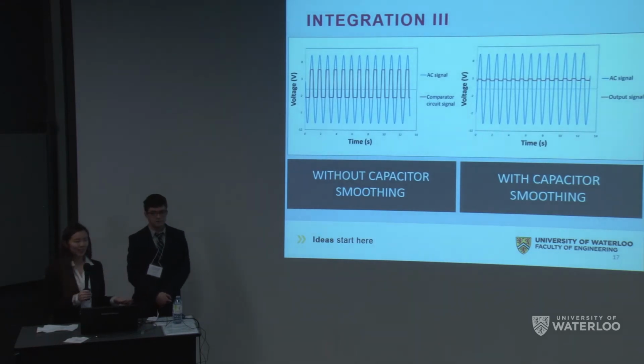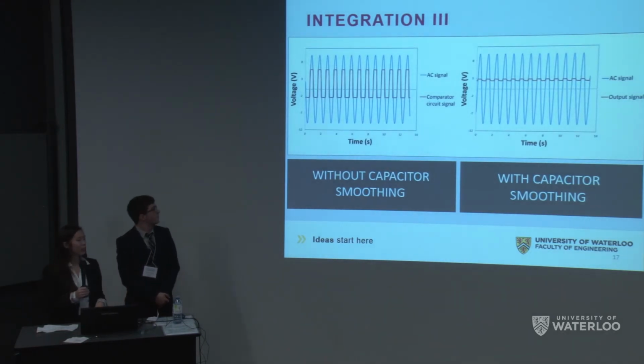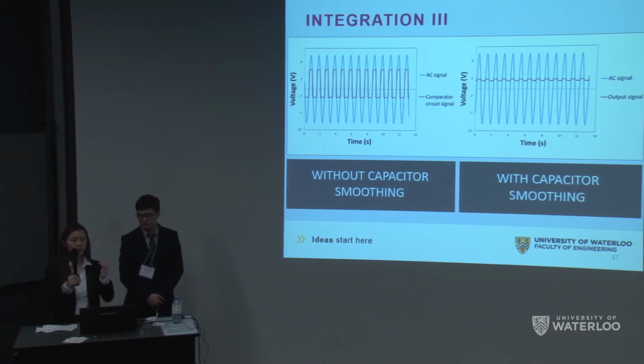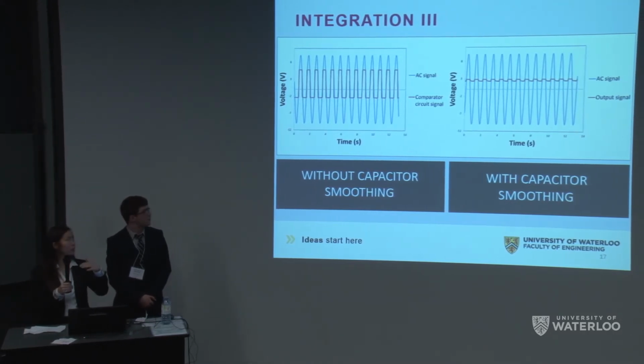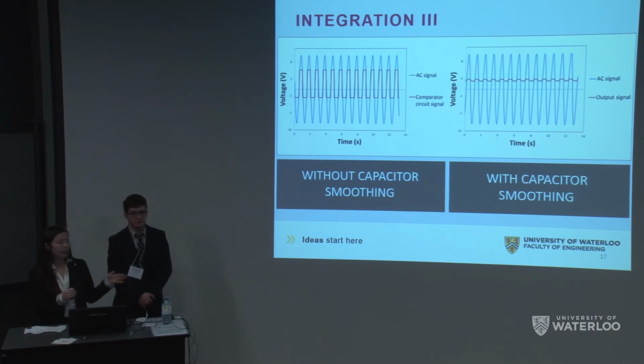So the principle of the circuit is shown in these two graphs. The graph on the left has two signals. The blue is a sinusoidal curve, the signal generated with an output of 1 hertz. And it's analogous to the variable output of the film, because as you can imagine, the film bends and flexes, so it's not constant. And then the comparator circuit changes this into pulses. And then when you add in capacitor smoothing, you get a more DC-like signal.